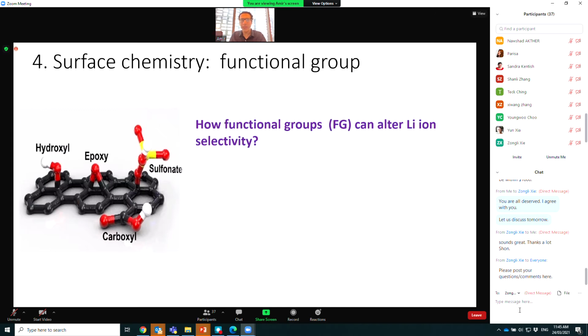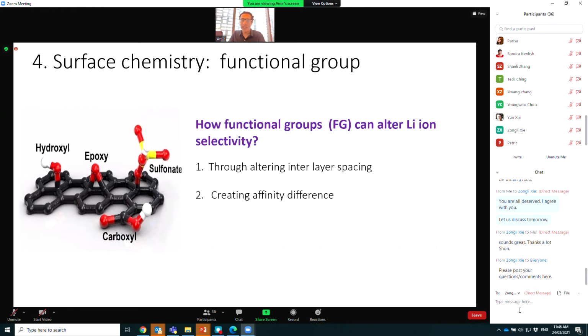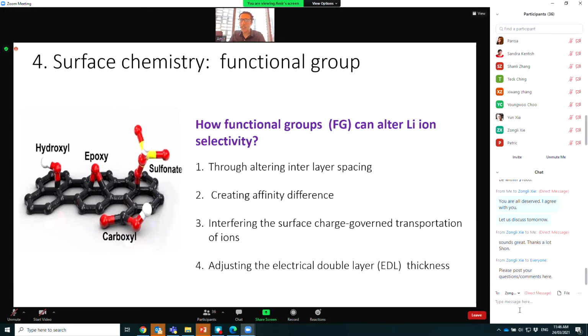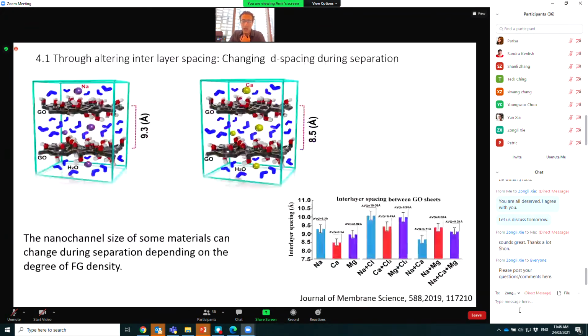The other parameter is surface chemistry, for example, functional groups. So how can functional groups alter lithium selectivity? We can alter it through altering interlayer spacing, creating affinity differences, interfering with the surface charge to govern transportation of ions, adjusting electric double layers, and a few more things. For example, for altering the interlayer spacing, we found that when we have only monovalent ions within the nanochannel, the channel size is somewhere around 9.3 angstrom, whereas when we had a divalent, the channel size reduced.